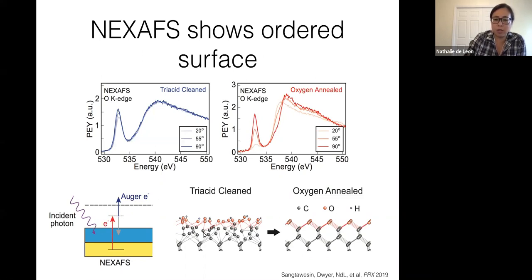So our general microscopic model for what the surface looks like, this is obviously a dramatized depiction, is that in the acid clean surface, we have a lot of disorder at the surface. So these bonds are sort of pointing in many directions, whereas in the oxygen annealed surface, we have mostly ordered rows of ethers. But we actually don't expect there to be a very significant chemical difference other than this degree of disorder.